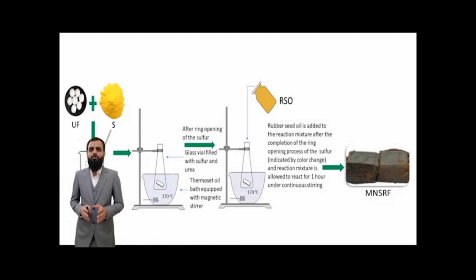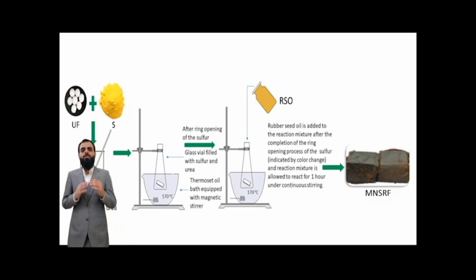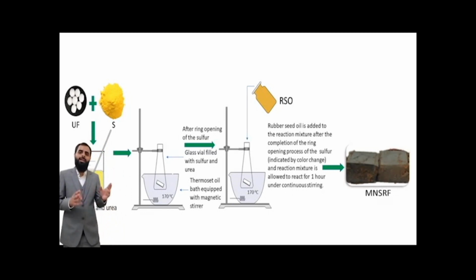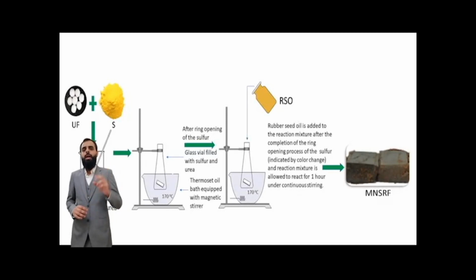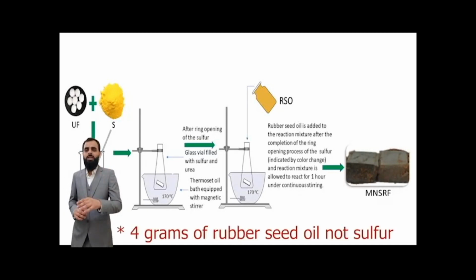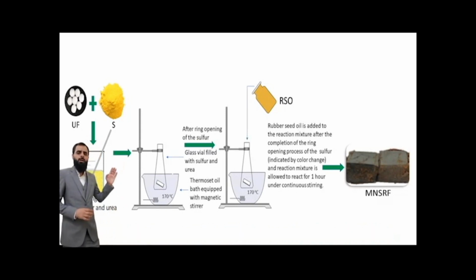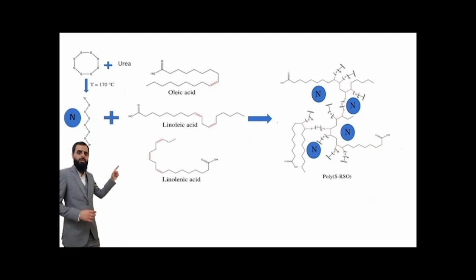Why are we melting sulfur? Actually, the melting of the sulfur initiates the ring opening process of the sulfur, which generates the diradical at the end of the sulfur chain. After the melting of sulfur, we pour 4 grams of rubber seed oil inside that mixture and let that mixture react for 1 hour. Inside this glass vial, this reaction occurs, which involves the ring opening process of the sulfur and then the reaction of the diradicals with the rubber seed oil.